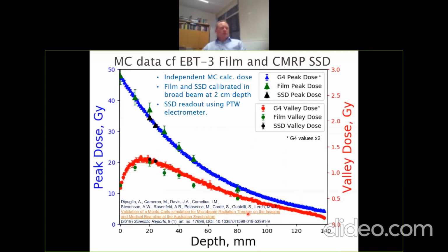Depth dose profile. Both in the valley region, between the microbeams, you can see a very different depth dose profile compared to the peaks. Then we can get a comparison of our Monte Carlo with our detector system. This is film and our silicon strip detector. This was recently published just last year.